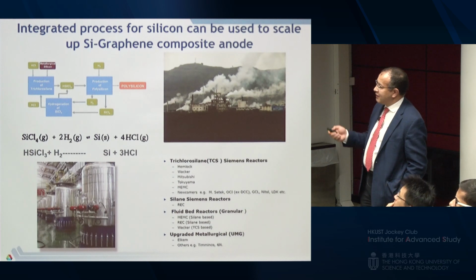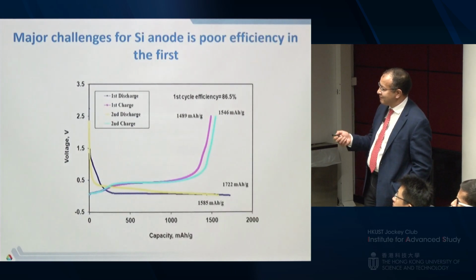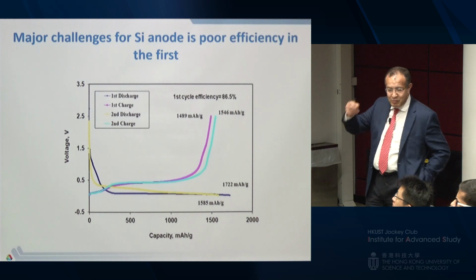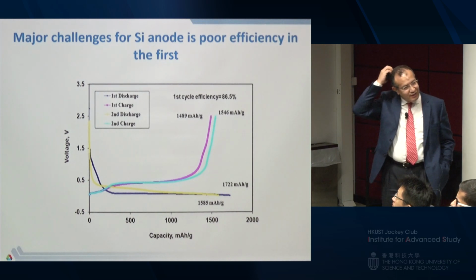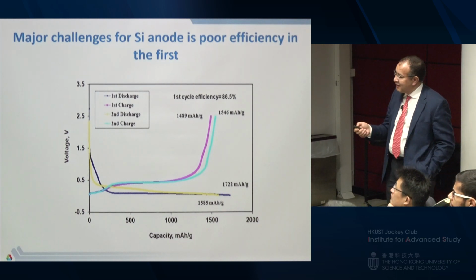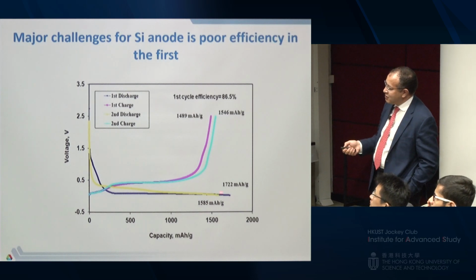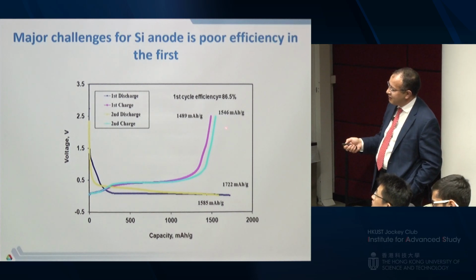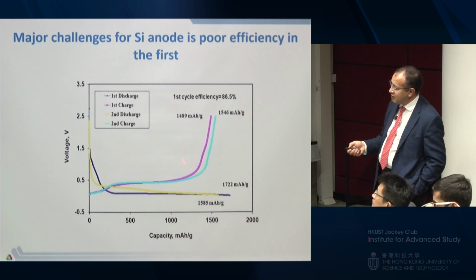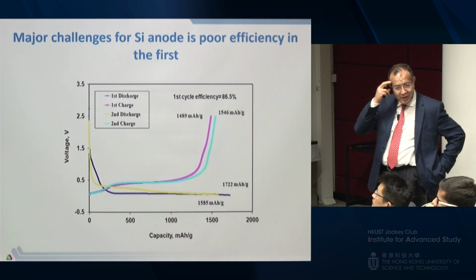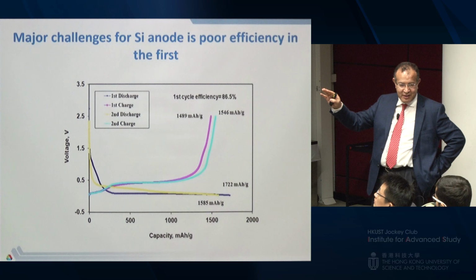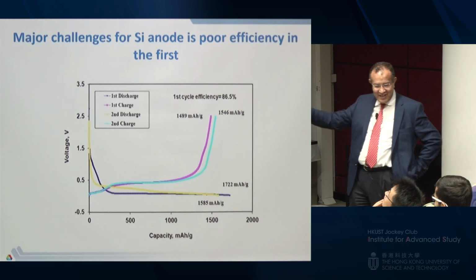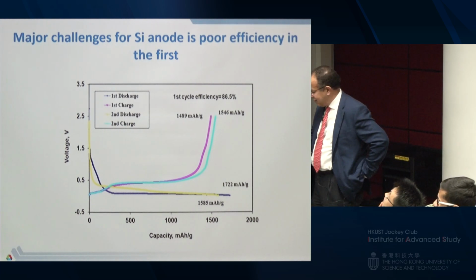So here is the other problem with silicon, is the poor efficiency there in the first cycle. Now, this is a discharge. The charge is about 1,700, and the discharge is 1,500. So the difference is about 200 milliampere hours per gram. This is one of the best samples, by the way. There are samples that have more than that. So imagine 200 milliampere hours per gram.